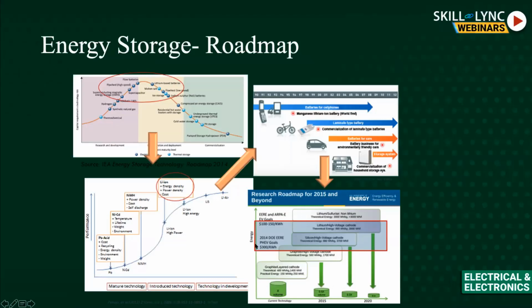And if you see here, at 2015, we are already reaching about 990 watt hour per kilogram or 3000 watt hour per liter. And if you imagine what I described in my previous slide, we are pushing from as much as 100 watt hours per liter in a lead acid system to as much as 3000 watt hour per liter. And that improvements in technology have made electric vehicles like Tesla or Nissan possible these days. And we are right now in the boom of going all electric.